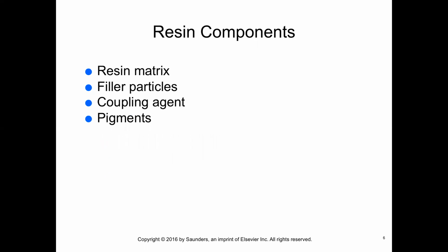The most commonly used resin for the matrix of composites is bis-GMA, which is a bisphenol A glycidyl dimethacrylate. Another resin that is used for the composite matrix is urethane dimethacrylate, which is UDMA. These resins are thick liquids made up of two or more types of organic molecules called oligomers. To reduce viscosity and allow the loading of filler particles, a low molecular weight monomer is added.